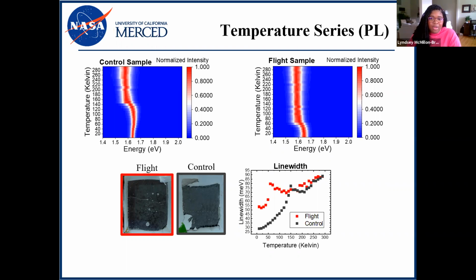And this value of 55 K is much lower than any transition observed in the literature. Typically, perovskites make this transition anywhere between 150 to 130 Kelvin. If we look at both samples, the peak emission energies for each sample is about the same, at about 1.68 eV, I would say. But the flight sample is still a lot more stable. Now, this is desirable because the tetragonal structure is ideal for photovoltaic devices, because power conversion efficiencies are much better than that of a device made from orthorhombic crystalline structure.